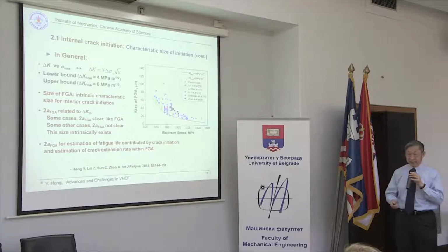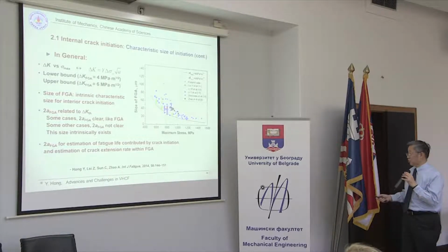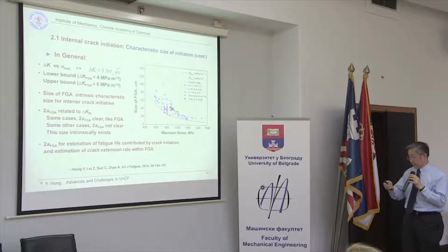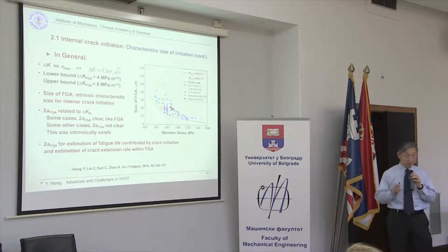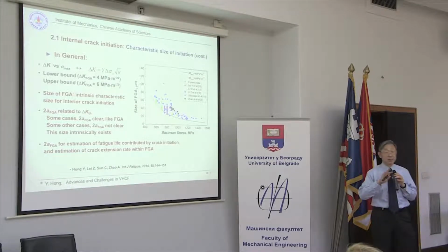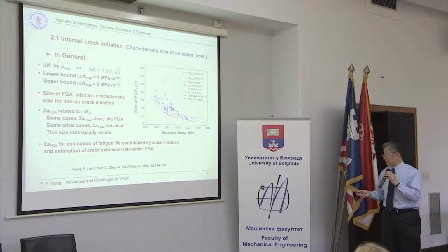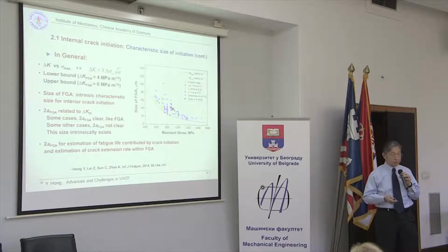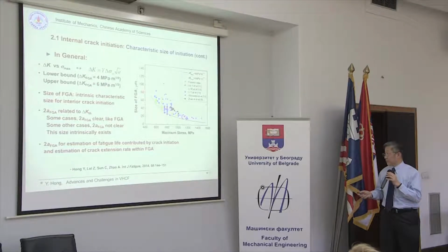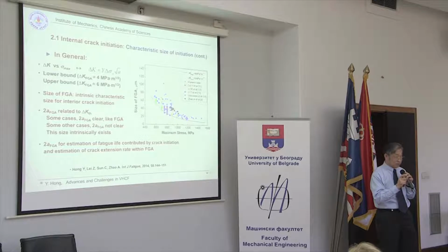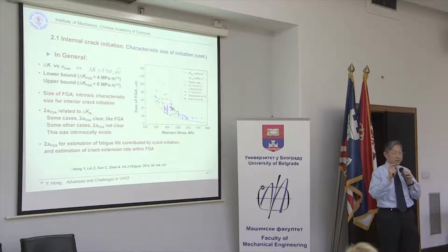And we collect a large number of data from the literature to show the size of FGA as a function of maximum stress. And we see that most of the data are within the lower bound of 4 megapascal root meter and the upper bound of 6 megapascal root meter. So we say this value of delta K for this initiation region is very stable for different loading cases and different sizes of initiation region. No matter how these change, the delta K value is very stable.